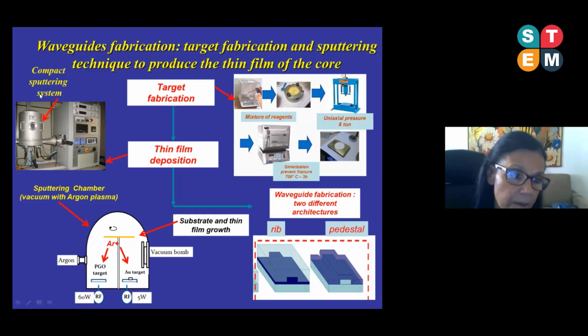And in this figure, the compact sputter system that we use for the production of the thin films. In this figure, I illustrate the inside of the sputtering chamber. The sputtering chamber operates in vacuum with plasma of argon. And the substrate where the thin film is grown is placed above the two electrodes where the targets are placed: the target of gold and the target of the host.